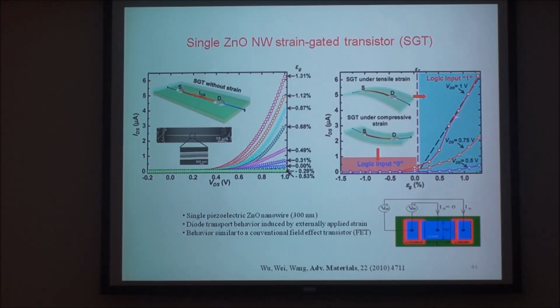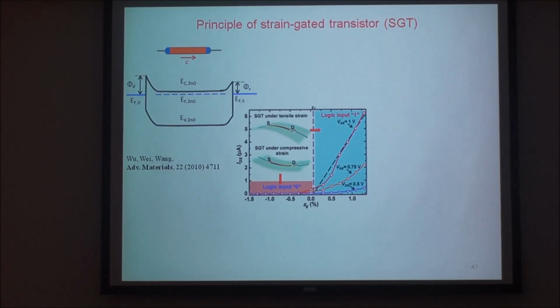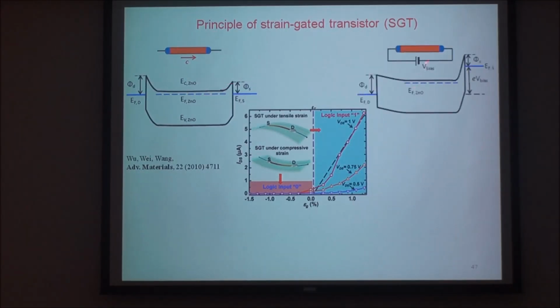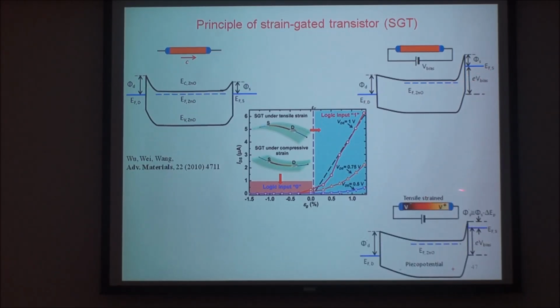Compressive is off. Why? There's a switch effect here. It used to be that this is the gate voltage, but now it's strain. Why is it so? In such a device, besides the voltage we applied, which offsets the Fermi level by a difference because of the bias applied here, besides this external voltage, there's an inner crystal potential. When you apply the strain, the piezoelectric produces an inner crystal potential.